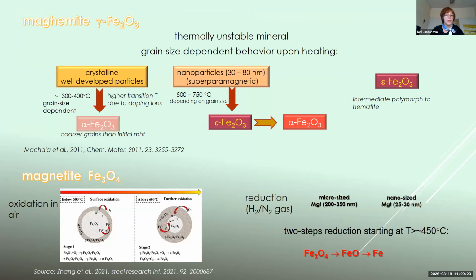Maghemite is also thermally unstable mineral, and it also converts to hematite, but it's established that the magnetic properties are grain size dependent. And one interesting pathway is the transformation of superparamagnetic nanoparticles of maghemite, which can transform in a pathway through formation of specific polymorph of hematite, the so-called epsilon form, which has very interesting magnetic properties, but I will not speak on this topic now. And magnetite again converts to hematite upon heating in air, starting with surface oxidation to form a maghemite shell, while in reducing conditions, it converts to metallic iron.